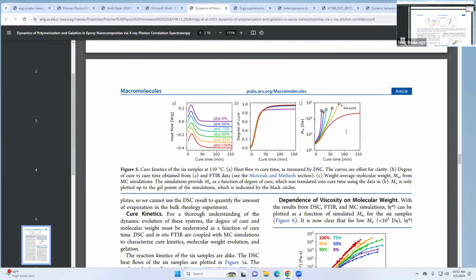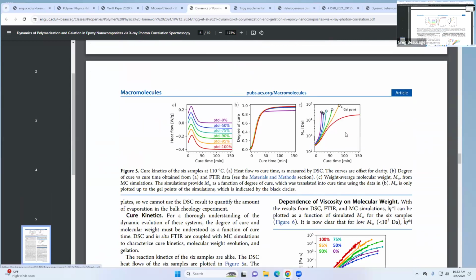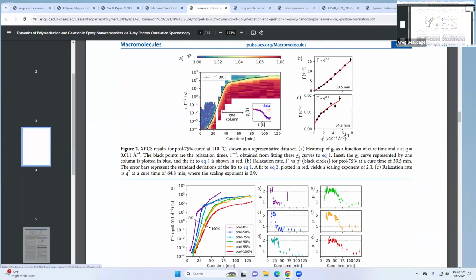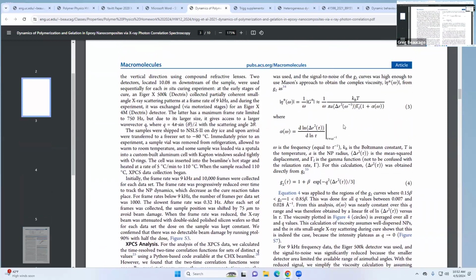Well, they also got the complex viscosity. I guess I skipped over that. So they used basically the Stokes-Einstein relation, which says that the diffusion of that particle is going to be related to its size and the viscosity of the medium around it. So they use the diffusion constant to back calculate what the viscosity would be at that point. So they could actually now not only track the dynamics, but they could track the viscosity growth in their material, basically using what we call a microrheology approach.